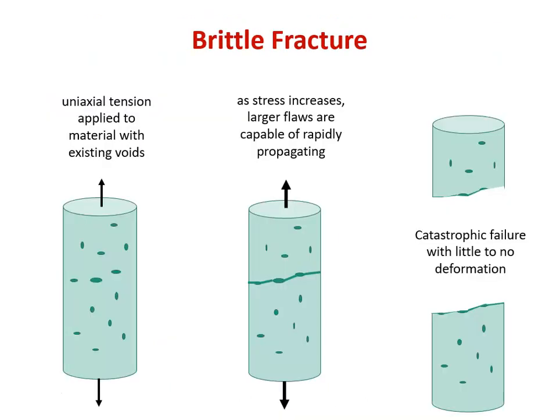Okay, flip side, say we had something more like a ceramic. So in this case, we're showing the material with its pre-existing flaw distributions. So we have the pale green tensile sample. This could be maybe a multicrystalline ceramic or a very, very brittle metal, maybe something like tungsten or iridium. And the dark green little ovals in it are a schematic representation of your flaws, your flaw distribution. So these are little cracks, little voids. If we sintered this as a ceramic or a powder metallurgy product, it would be the voids between the grains,